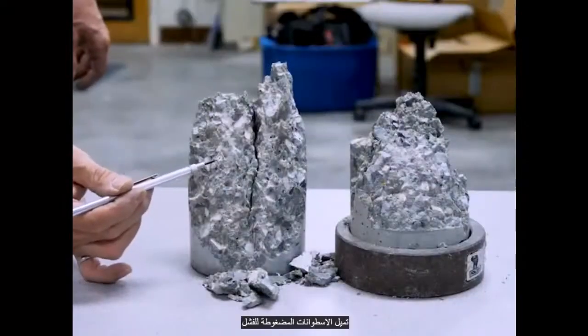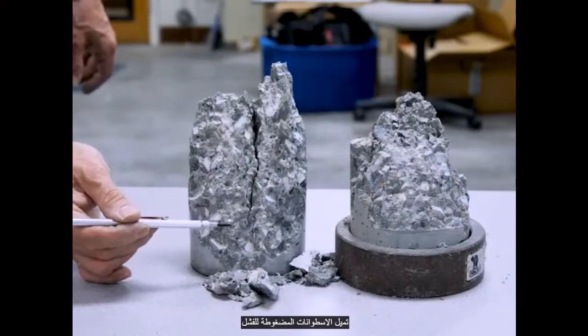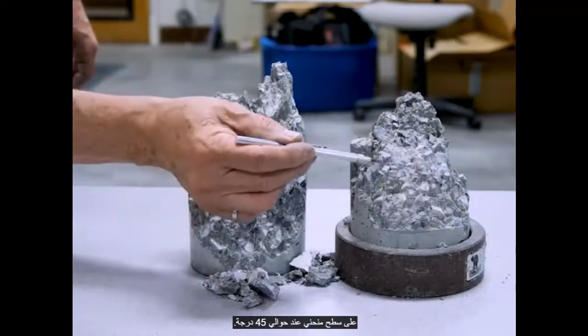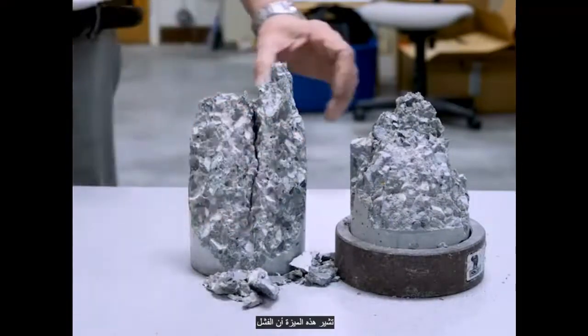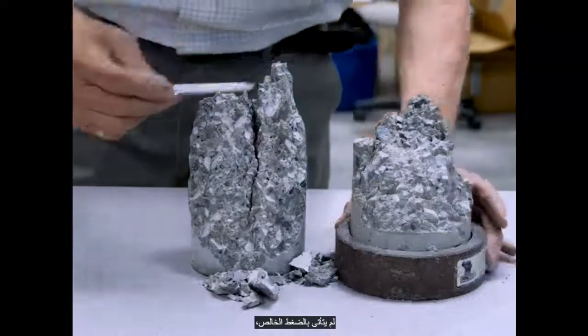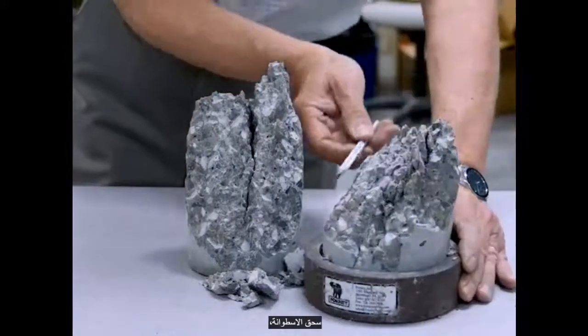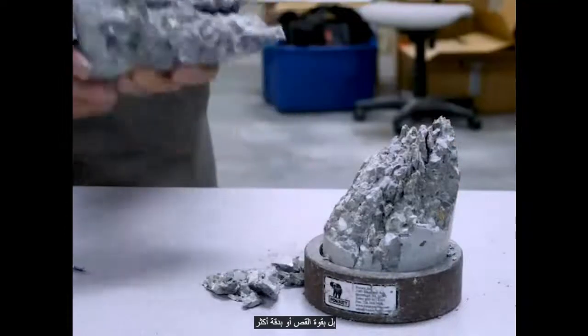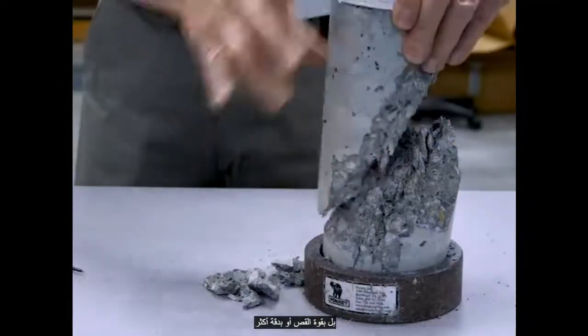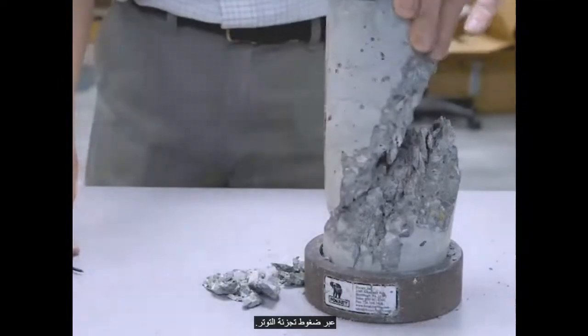The cylinders in compression tended to fail along an inclined plane at roughly 45 degrees. This feature indicates that the failure was not driven by pure compression, crushing of the cylinder, but rather by shear forces, or more precisely, by splitting tension stresses.